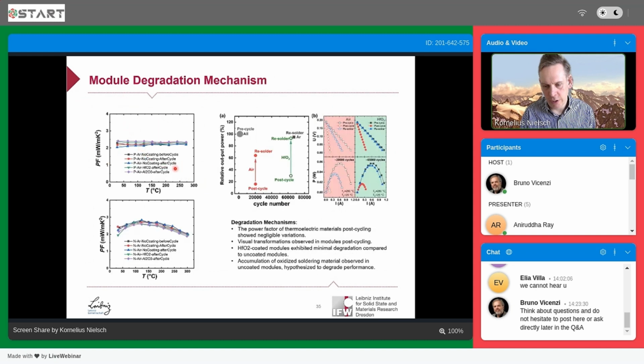One of the features I want to mention especially is that we could also do some robust tests of, let's say, several thousand cycles in air, also with the hafnium oxide coating. And if we, for example, after this long-term test, remove the soldering and resolder the whole module, we can see that we came nearly back to the initial behavior of the whole module.